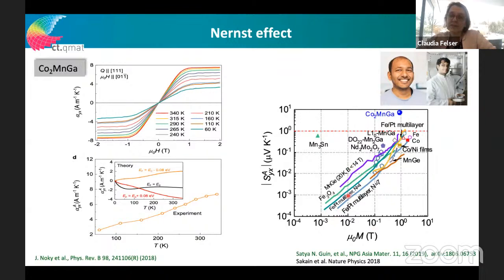So it looks a little bit linear, but if you look closer, especially at this material with the crossing point, cobalt-2 manganese gallium, but you see also manganese cobalt, manganese-3 tin, which I discussed in the beginning, shows also a giant response compared to the tiny little moment you see in this material. So it's orders of magnitude larger.